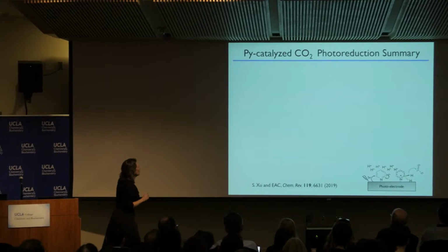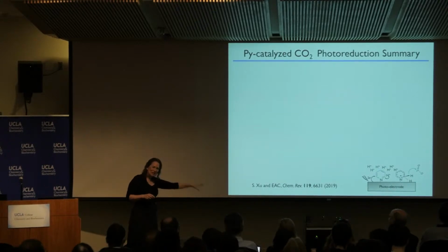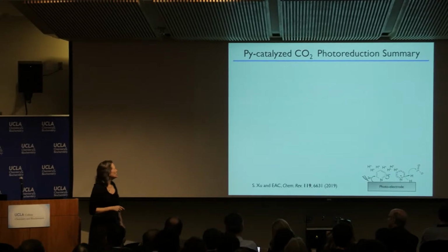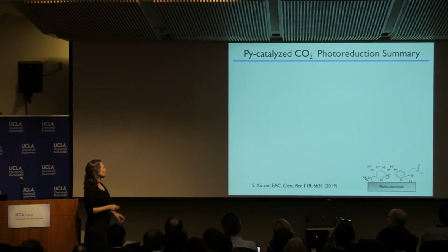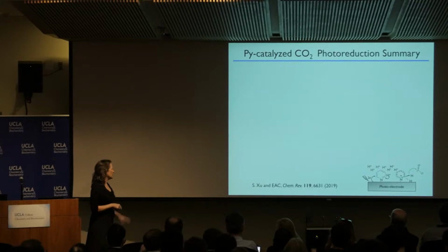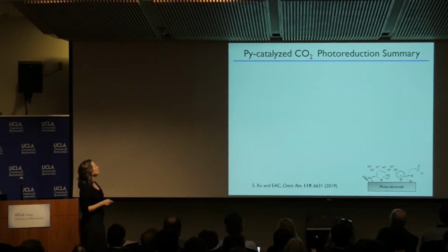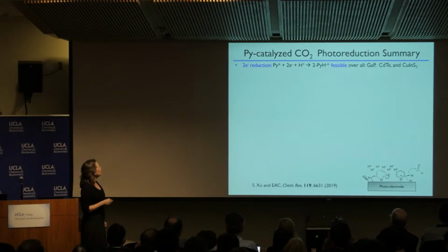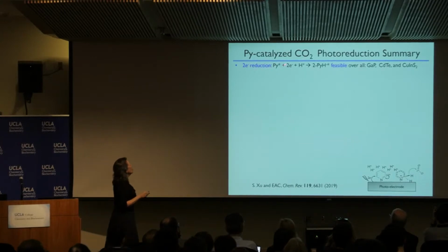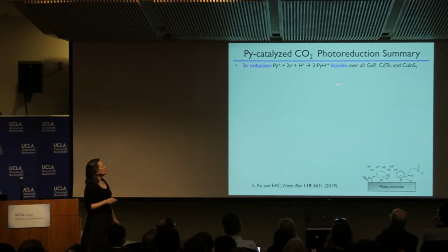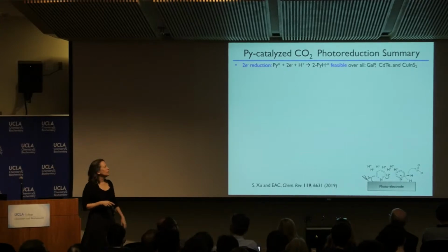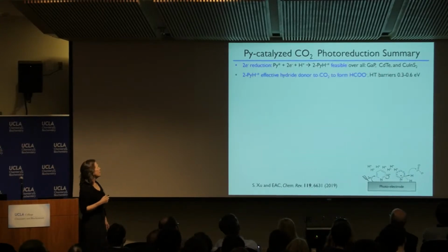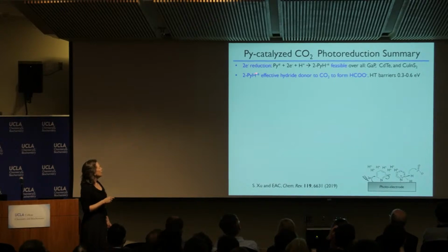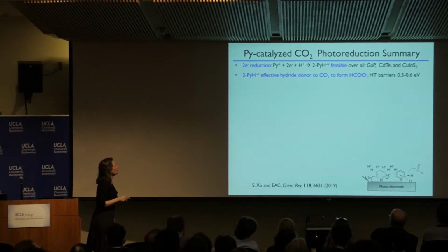So to summarize this many years of work by many people in my research group, what is the overall picture? And you can read about it in this Chemical Reviews that has a lot of other people's work as well on CO2 reduction. And basically what we believe is happening is that you get a 2-electron, 1-proton process. It's this hydride process that we've shown is feasible under illumination on all of these semiconductors. And essentially, once you make that, you can very fastly transfer hydride to form formate. The barriers are all reasonable.